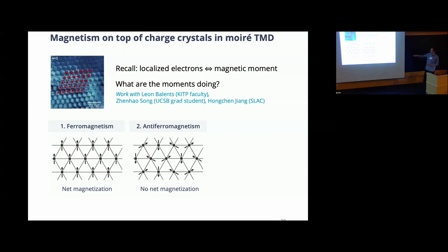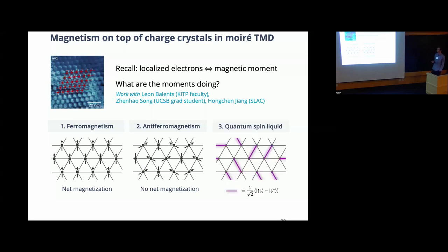So here, on the triangular lattice, these moments, or these arrows, are basically rotating in a 120-degree pattern. And if you now sum them all up, you can see that they exactly cancel. So you don't get any net magnetization, but still there's some notion that at each lattice site you have a small arrow pointing in some direction. And the third possibility, and this was actually work that I did here together with Leon Balents, KITP faculty, and Zhenhao Song, a UCSB grad student, and Hongchen Jiang, who's actually visiting at the moment, who's at Stanford Accelerator. The third possibility is here that the system might form a quantum spin liquid.